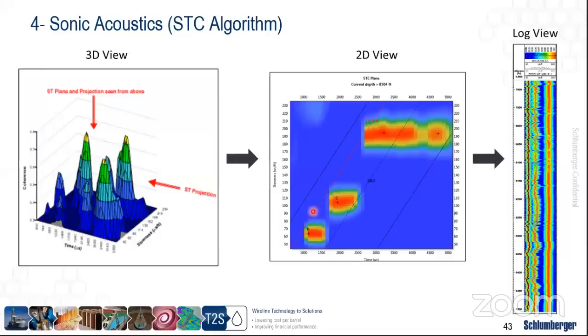So this cross plot, or this snapshot, if you're looking at this histogram, is a view of this coherence, time, slowness from the top side. So if we look from this top side, we're looking at the time versus slowness. The bigger the amplitude of these peaks, the more bright spots there will be, which in this case are red spots, which show high confidence. The fewer peaks we have around this area, then we have these blue spots.